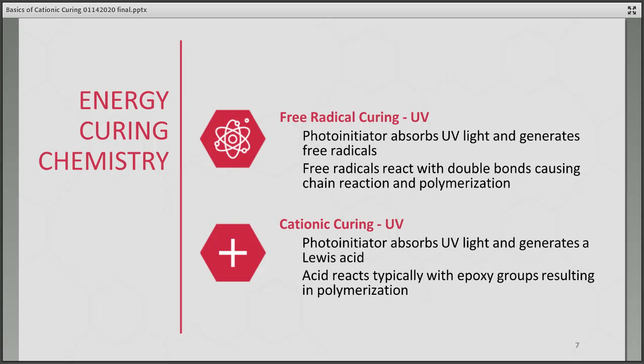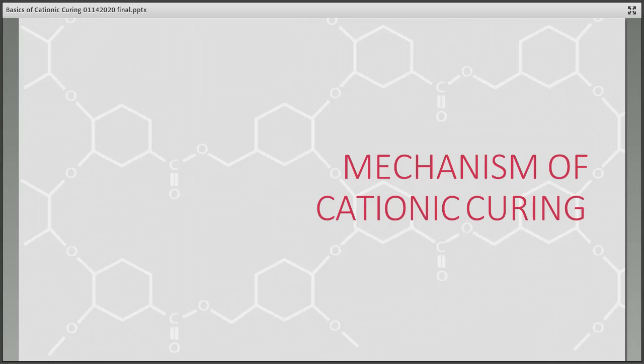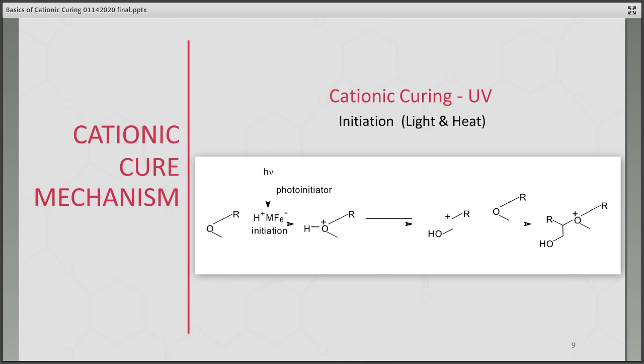Here you use a photoinitiator, it absorbs the UV light, and it generates, instead of a free radical, a Lewis acid. It's this acid that reacts typically with epoxy groups, resulting in the polymerization. So instead of generating a free radical, think of it as a very similar process. You're now generating an acid. So to illustrate this, we're going to talk about the mechanism of cationic curing.